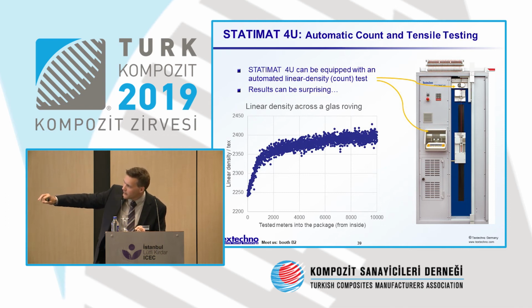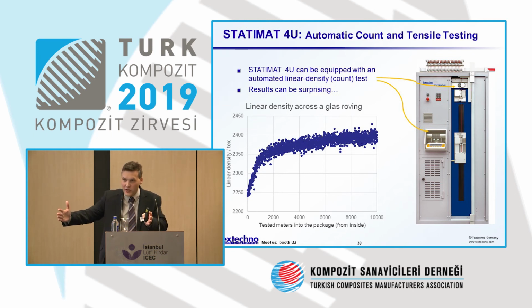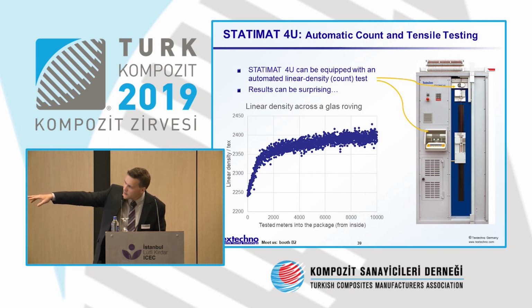It does this fully automatically, and we had a customer coming in, he was complaining that the yarn, the roving he was buying, the glass, actually was out of specification in terms of weight per unit length. And this machine was used now to check 10,000 meters, that's basically a full bobbin of glass fibers, to check the linear density, and it does it on pieces of 5 meters, next 5 meters, next 5 meters, several thousand times. It does it fully automatically, and we see the linear density that it has measured on the left-hand side. And you see in this curve that we're actually starting low, around 2,250 TEX, whereas the vendor specification for that roving was actually around 2,400 TEX.